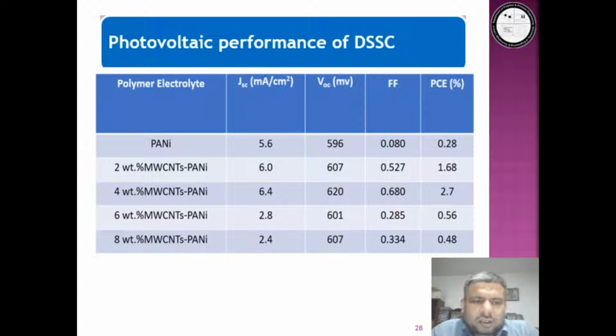The solar cells fabricated with optimized quasi-solid state electrolyte or polymer gel electrolyte revealed superior performance, as you can see in the table. However, it also shows that the performance of the cells goes down at higher CNT and salt concentration. So what could be the reason? At higher CNT contents, agglomerates form, act as trapping sites and provide a hindrance to the flow of electrons. Similarly, salt remains undissolved at a higher concentration, providing resistance in the flow of electrons. Thus, the efficiency or performance of the cell drops at higher concentration.